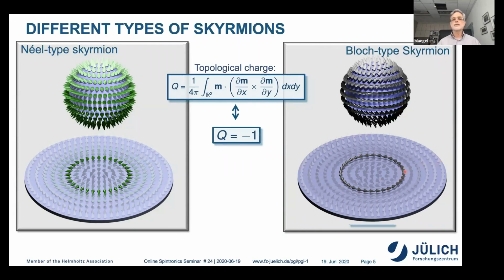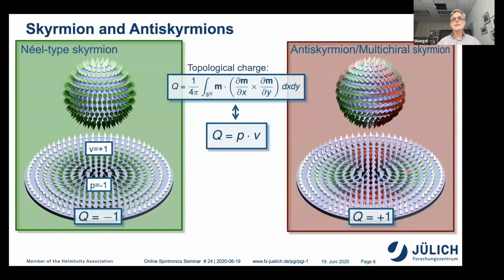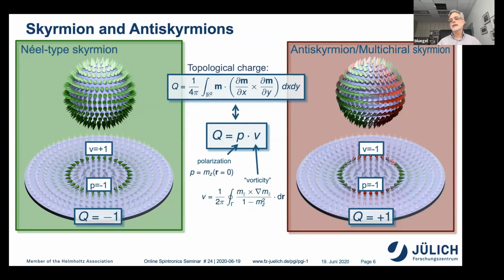tangential to the radius. Then we have skyrmions and antiskyrmions. What is the major difference of this? So this topological charge can be written as a product of a polarization, which is the magnetization at the origin, times a one-dimensional winding number. Sometimes in physics, we call this the vorticity. It's a one-dimensional winding number where you take basically the integral along a circle, and you calculate a one-dimensional integral. And you see here the integral is different. Here the vorticity is +1, but here the vorticity changes sign, and the vorticity is -1.